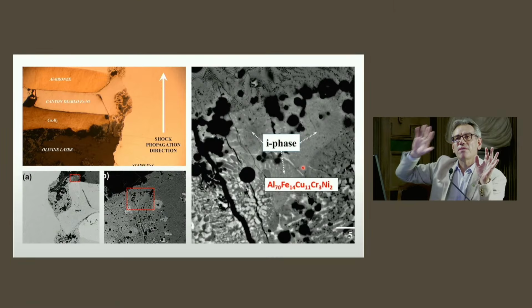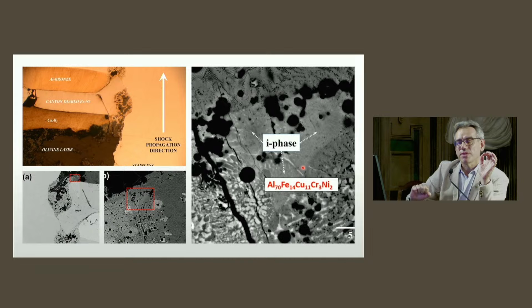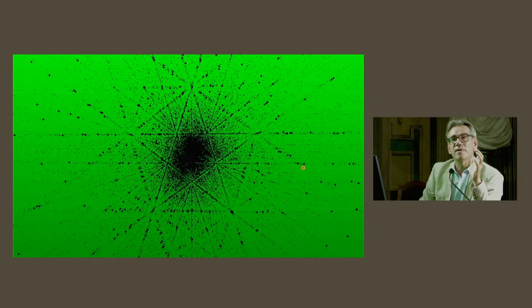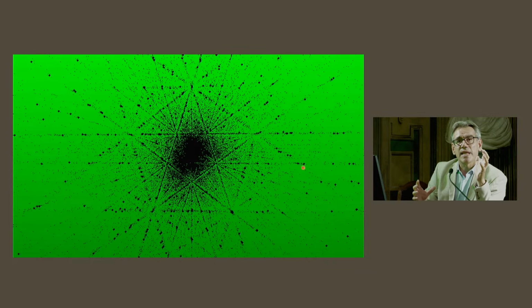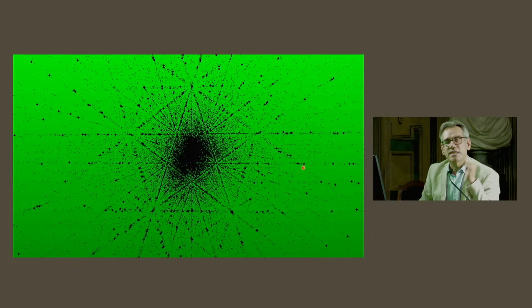You have to know that quasicrystals, even if they are very small, are very highly diffracting. I'm going to show you all the collected data from this small crystal down the 5-fold symmetry axis in stereographic projections. The image is actually terrific - look at all the reflections, they fall perfectly on the 5-fold symmetry. But even more important, look at the structural perfection of the quasicrystal, which seems impossible, because all the quasicrystals we produce in the lab are made under perfectly rigid, strict protocols of formation. Here we are very far from equilibrium, in a completely inhomogeneous medium, and yet we produced this kind of material.